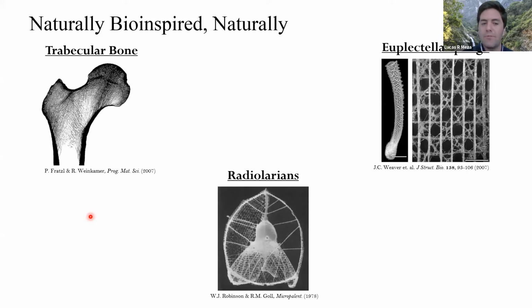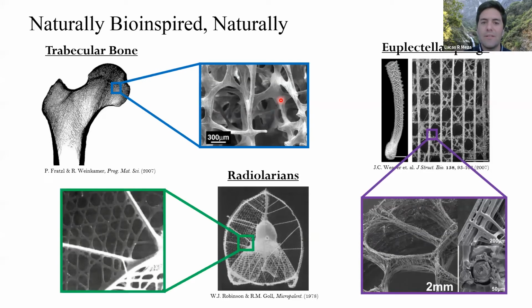Where we see this most dominantly, in the engineering world we're just starting to scratch the surface of this, but a lot of our inspiration actually comes from natural materials. If you look at trabecular bone, radiolarians, these sea creatures, sea protozoa, or Euplectella sponge, which is one of my favorite creatures, also a stellaceous sea sponge, you look down at the small scale and these are built up fundamentally at the nanoscale of these nanoscale constituents that are organized into some sort of architecture, which is organized into another architecture at another length scale up, and so on. This Euplectella is very interesting, a really good example of that, because at the smallest level you have these tens of nanometer thick brittle sheets that are organized into a core shell composite with a polymer interlayer between them.